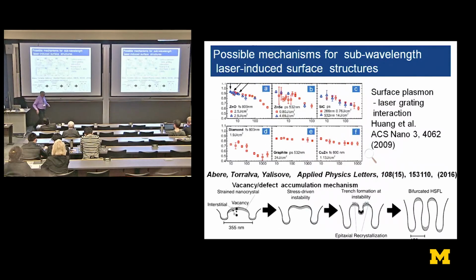I'll mention another paper. Steve Yalisove's one of my collaborators, and Ben Torralva here in the MSE department. They came up with a very interesting observation recently in which a bifurcation occurs in the period of these surface oscillations driven by a laser. And they've associated that with a defect or vacancy accumulation in the material. This is basically a strain-driven mechanism that forces all the dislocations into a localized position